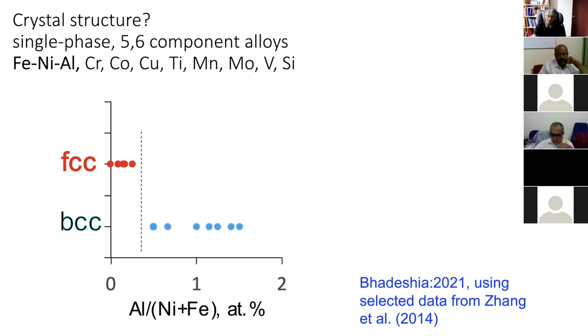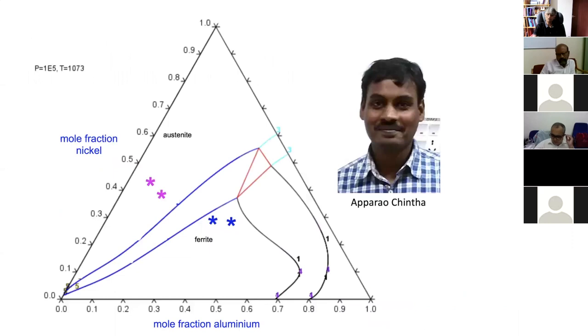And this work is not complete, but I asked Aparao Chinta in Tata Steel to calculate a ternary phase diagram section where we have just aluminium here, nickel, and of course we can work out the iron concentration as the difference between the 100 minus nickel and aluminium. And when we plot the same data, okay, and I've only plotted a few of those data, and this is for 800 degrees centigrade, this section, ignoring all the other elements, all right, only focusing on iron, nickel, and aluminium. Once again, the BCC ones found experimentally fall in the ferrite region and the FCC in the austenite region.